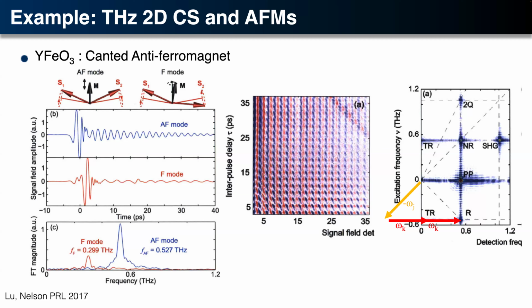And we call that the rephasing response. If you're familiar with the idea of spin echo or photon echo, that's the equivalent of the spin echo response. You don't usually use this perturbative language when you think about things like a Hahn sequence in NMR, but that's it right there. And then there are other ones. That's what we call the two quantum signal. So you excite the system twice and then de-excite it. That's like what we would call the pump probe. We were doing lots of work on metals, and on metals this is the principal and dominant response. You excite the system, de-excite the system, and then excite it again, and retain information about the material response all in the middle here.